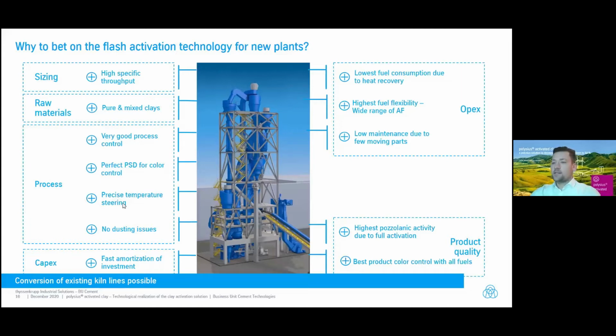So another thing is here, and this is, I think, one of the most important, the precise temperature steering. So I just told you that it is very needed to have the right temperature window for activation. We don't want to overheat the material. This would lead to a bad product quality. And the temperature for activation, we can steer very well in the flash activator.